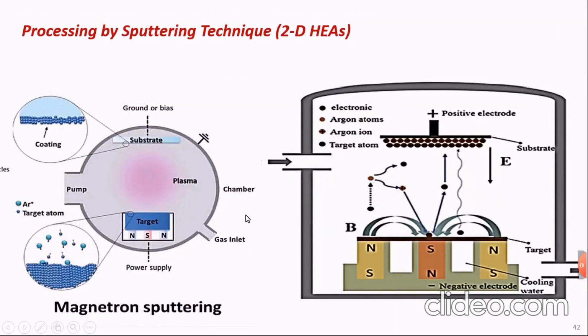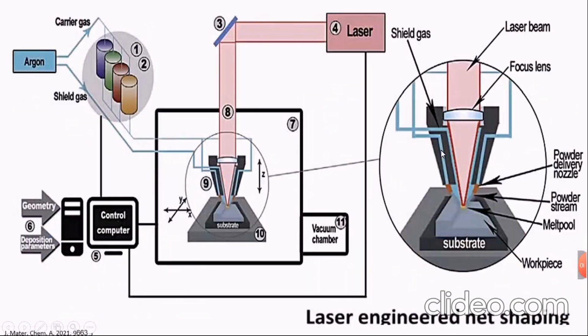For coatings and films, one of the famous techniques is the sputtering technique. The magnetron sputtering technique depends on depositing particles, which are target atoms, onto the substrate under a power supply. So this is the actual shape of the magnetron sputtering. Here you have your substrate, you have the target atoms, and by applying power, the target atoms move to the substrate.